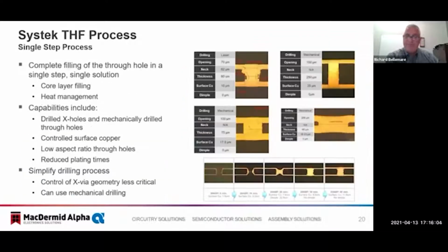And then the final process that I'd like to illustrate for you is a system that we use for heat management. The Systek THF process is a single step through hole filling process that can completely fill through holes in a single step in a single solution. This process has the capability to fill both laser drilled X-vias and mechanically drilled through holes, while minimizing the surface copper in order to maintain fine line capabilities.